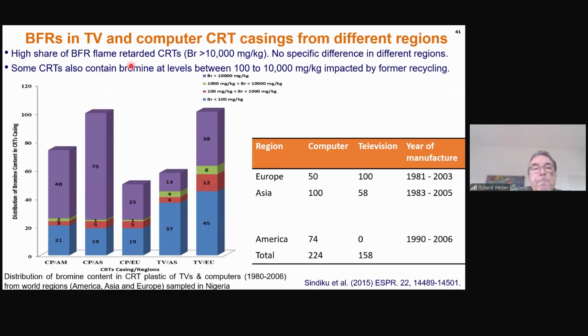So you see that a high share of these cathode ray tubes were flame retarded, here in purple. So you see that a large share of the computers here from Asia, also the computers from America, contain brominated flame retardants. Here for Europe, the rate was a little bit lower because our flame retardant standards are a little bit different. But you see overall the regions were not so different. We sampled from each region to understand if there is a difference. Finally, our conclusion was not a too big difference, but for Europe, the flame retardant use was a bit less.